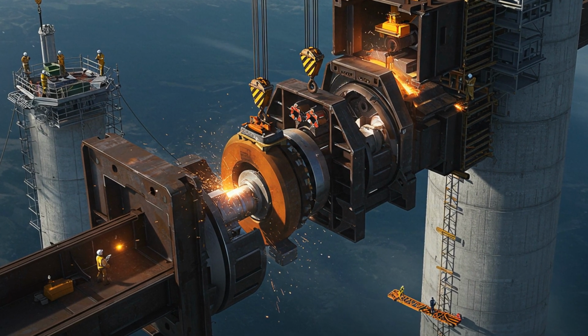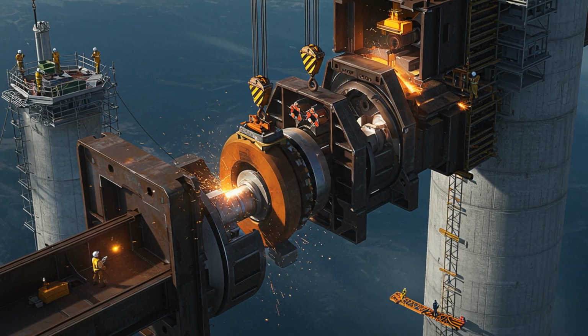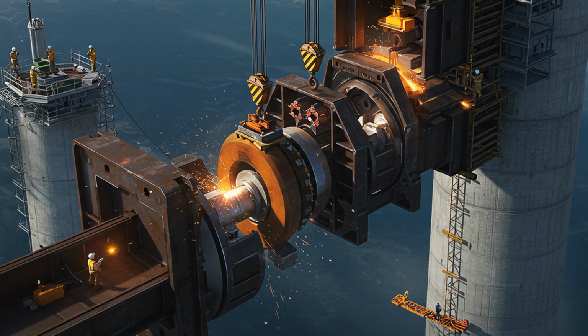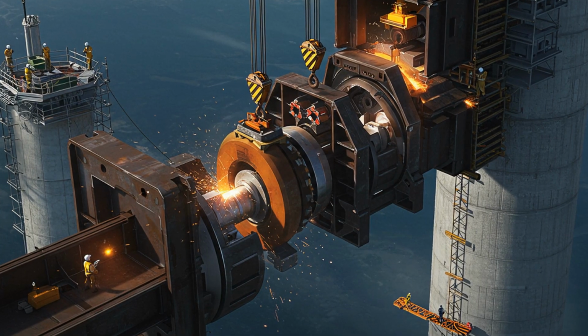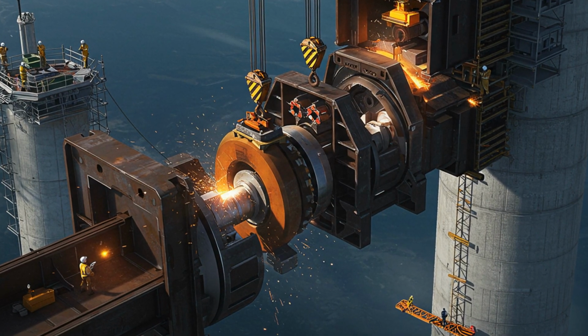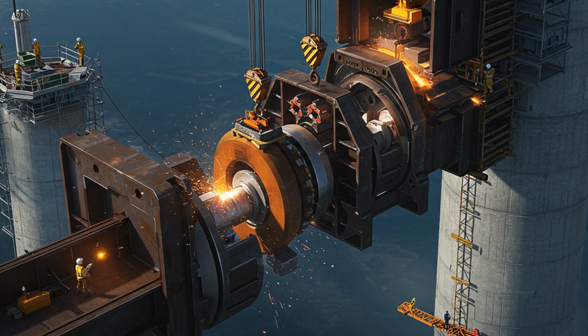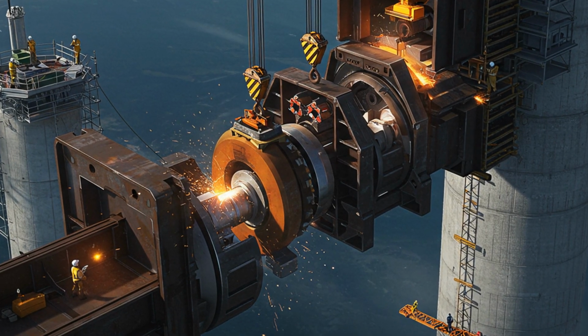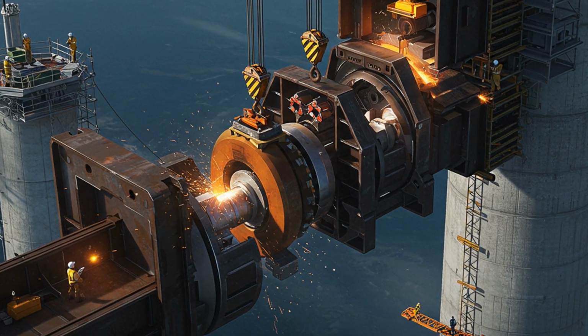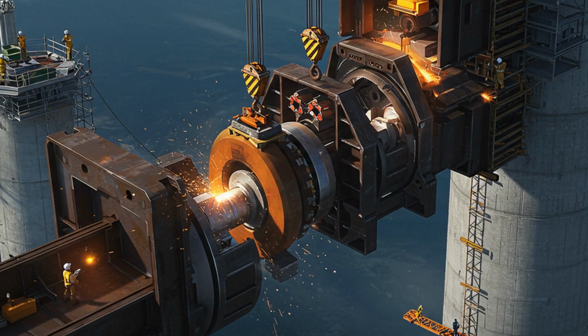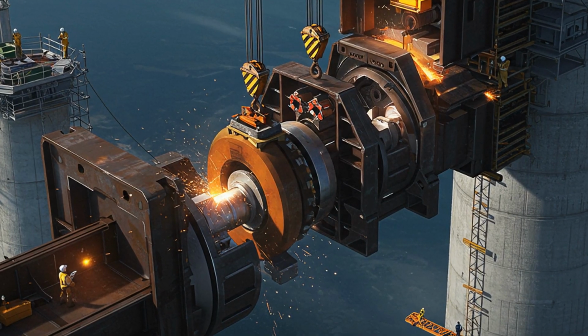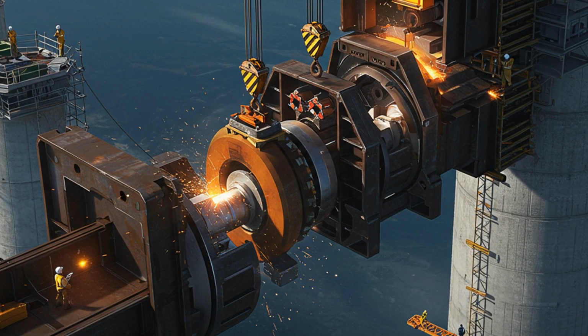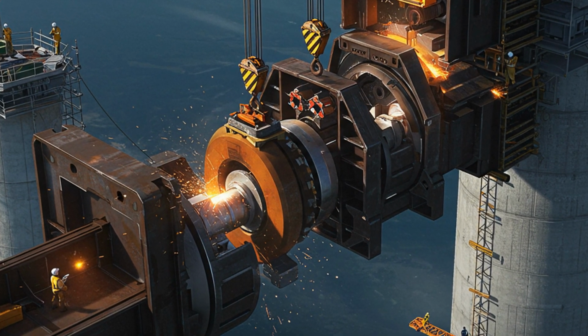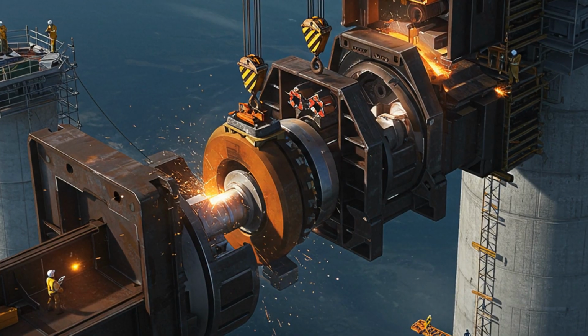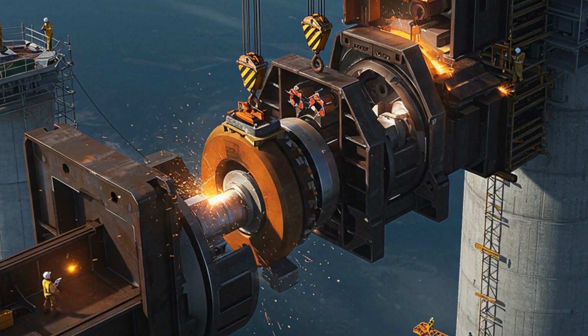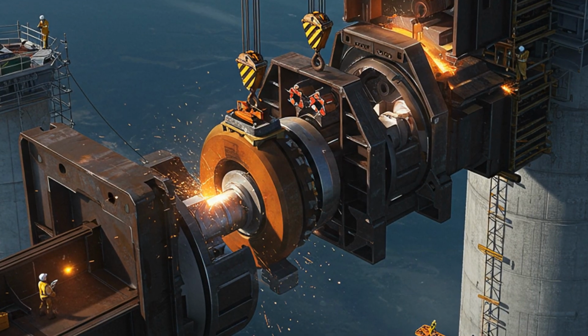Steel towers often arrive in sections, 50 to 200 feet long, bolted and then welded on site. Erection uses crawler cranes and synchronized strand jacks to lift heavy segments, each lift planned with crane charts, load paths, and safety factors. Once erected, towers are aligned within inches over hundreds of feet using survey instruments and total stations. Saddles at the tower tops carry the main cables and are machined to smooth curvature to prevent stress concentrations. Bolted connections use high-strength bolts pre-tensioned to a specified torque or measured via calibrated hydraulic tensioners. Every fabrication step reduces uncertainty because a misaligned tower changes cable geometry, and cable geometry dictates the whole bridge's behavior.